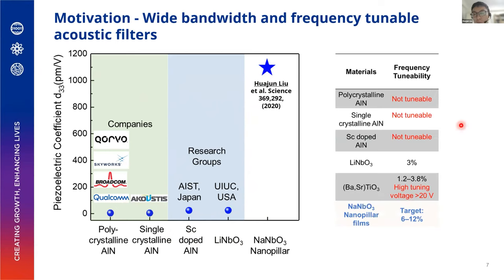And for the frequency tunability, aluminum nitride is not ferroelectric, so it has no tunable frequency, because basically the polarization is not switchable by the field. Lithium niobate and barium strontium titanate show some tunability, but based on the field-dependent piezoelectric behavior of our film, we think we should be able to reach a much higher tunable frequency range.